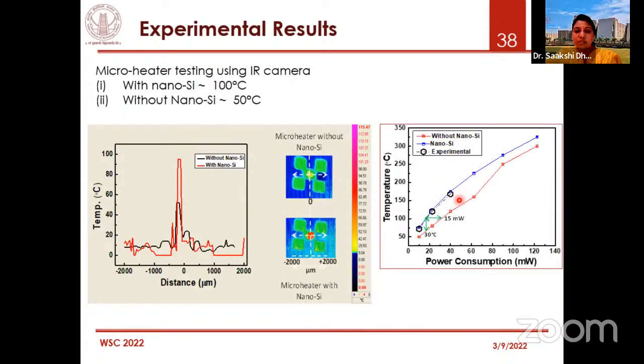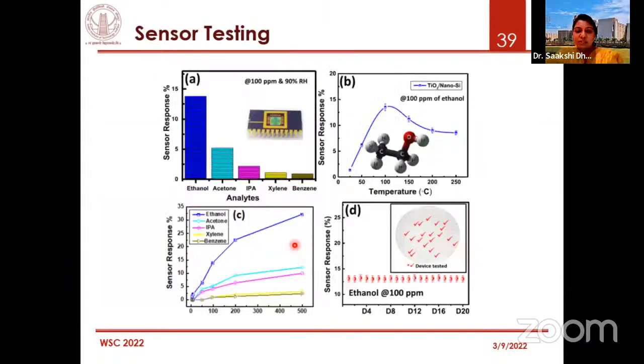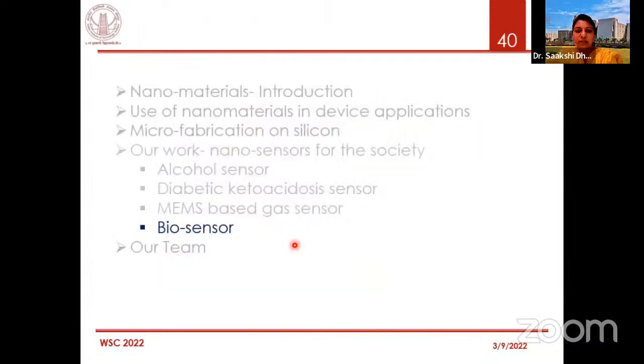It was published. We also did some thermal measurements using the IR camera. We did the simulation, and then to validate that, we could see the difference between the chips with nanostructured silicon and without nanostructured silicon. So this was one of the mini achievements that we could get.